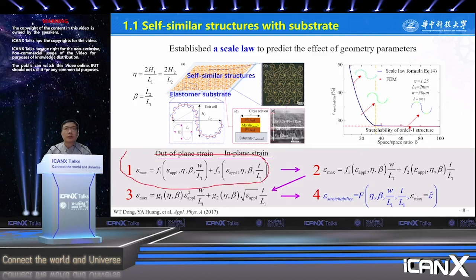the max strain is like equation 1, including two parts, one for out-of-plane and another for in-plane strain. The parameter eta is the height to width ratio, and the reduction ratio beta is the size ratio of the large structure to the small structure. Secondly, the effects of the out-of-plane and in-plane buckling with the geometric parameters W/L1 and T/L1 are computed by the finite element method, and the result shows that the maximum strain is linearly proportional to these two parts. So one can get the scale law like equation 2.